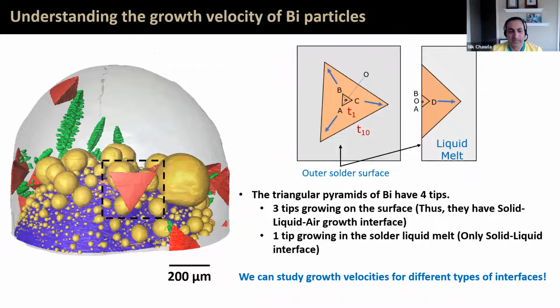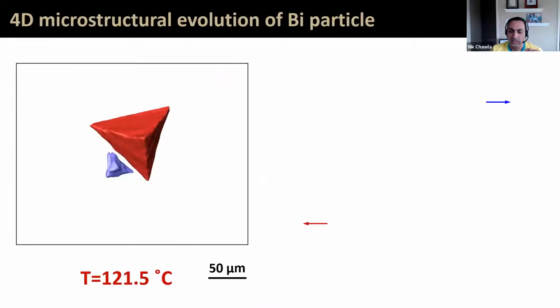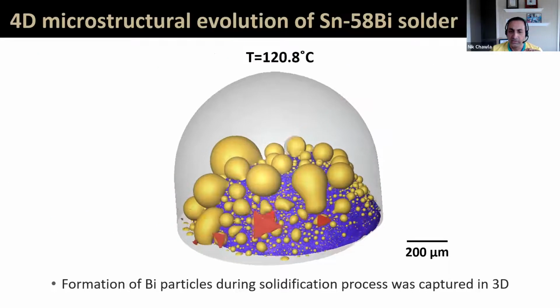Okay. So for that only we need a particular cooling rate actually. Yeah, for growth of nucleation. Cooling rate is the time factor, right? So a slower cooling rate gives more time for diffusion. And more time for diffusion means that we can actually get the bismuth atoms to go and agglomerate and form the solid. So if you notice in the water quench case, let me go back here.